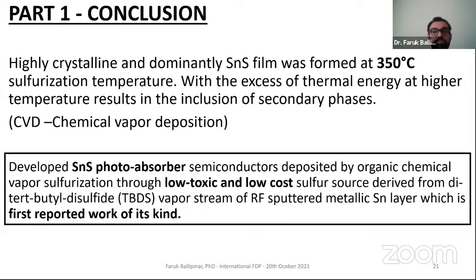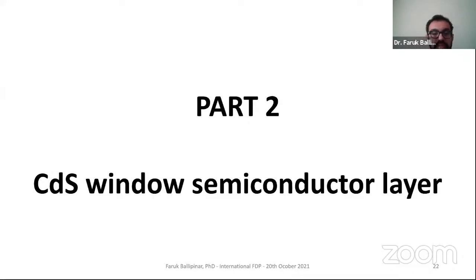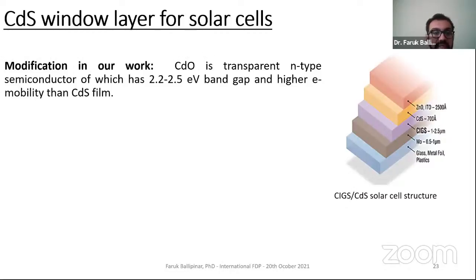Okay, so for the first time, using the TBDS low cost, low toxic sulfur source, we developed the tin sulfide thin film photoabsorber material, at atmospheric pressure. The second part is the N-type layer in the solar cell device. Cadmium sulfide is very common for cadmium telluride, CIGS, CZTS, for many types of inorganic thin film solar cell materials, because it has very good band alignment with the P-type layer. Because of these advantages, many people prefer to use cadmium sulfide.